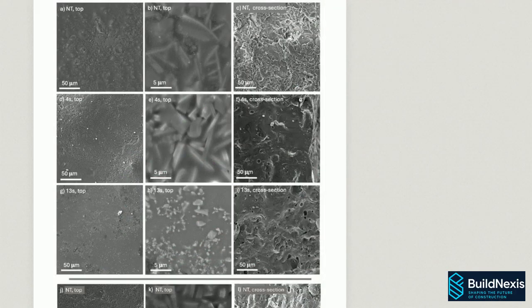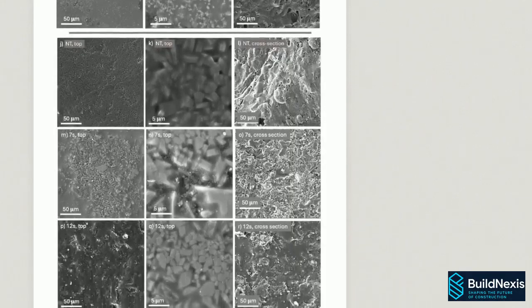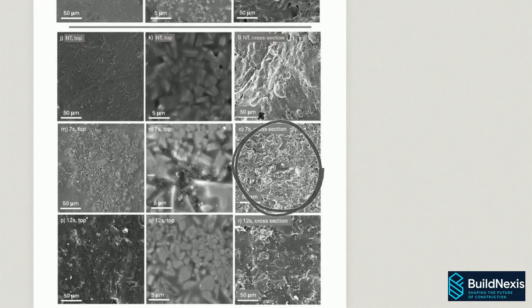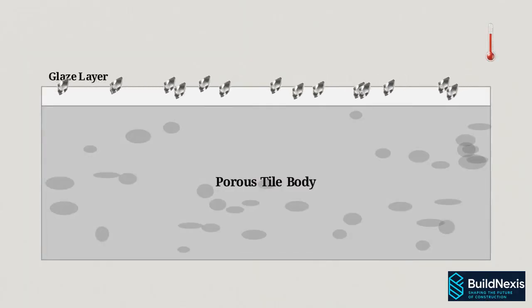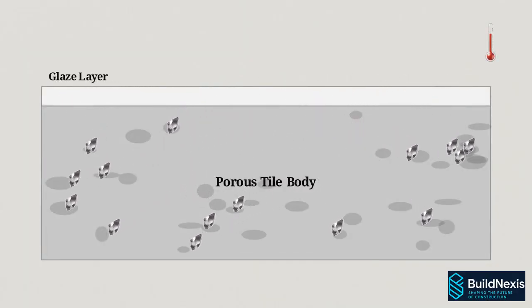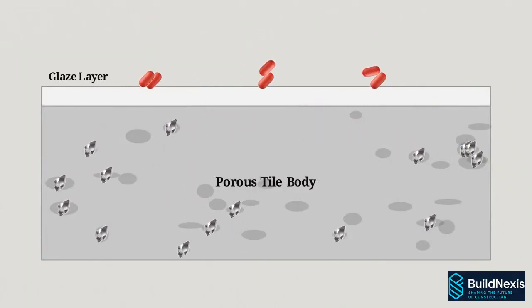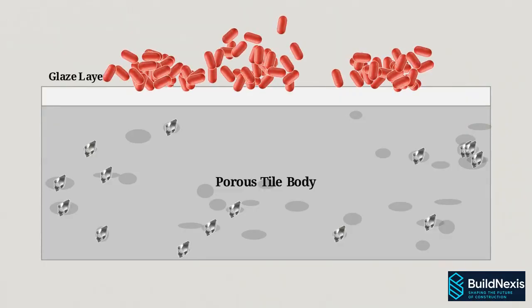Microscopic analysis explains why. When we look at a cross-section of the treated tile, we see a rough, highly porous internal structure beneath the top glaze. X-ray scanning revealed that under the extreme heat, the silver liquefied and diffused deep into these useless, porous internal layers. The silver survived the kiln, but it was lost to the depths of the tile. Because the heat sank the active agent, the top glaze was left entirely defenseless against pathogens.